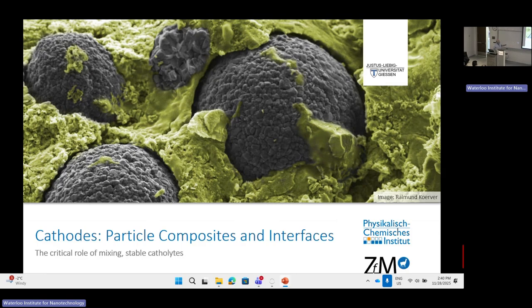Okay, let's go to the cathode side, where, of course, contact is also quite an issue. These cathode particles and cathode materials breathe if you charge and discharge, and they change volume. The radius isn't changing too much, maybe 100 nanometers or something, but it's enough to open up a crack to a solid electrolyte. And that can so far only be solved by having strong stack pressure. And often cells are being cycled at 100 megapascal. No way. No car would have enough; you would need quite some steel around your battery to keep 100 megapascal during operation in a car, and that is, of course, compromising the advantages of your cells.